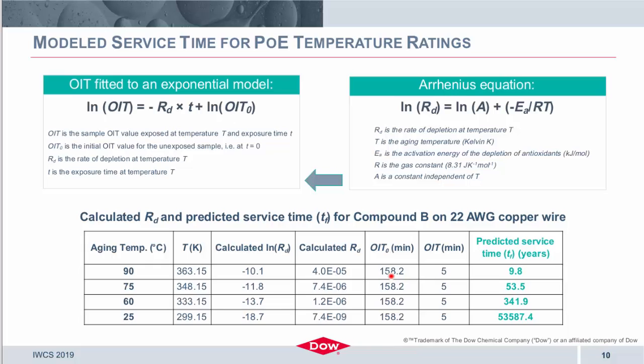without any aging. And as I mentioned, for OIT in this case, we used 5 minutes as a, quote, failure time. And when you put it all together back into the equation, at 60 degrees or 75 degrees for a rated cable, again, given that this is a conservative estimate of operating temperature or temperature environment that this cable would theoretically see in a consistent manner, you're still talking about predicted service times of well over 50 years under today's environment.